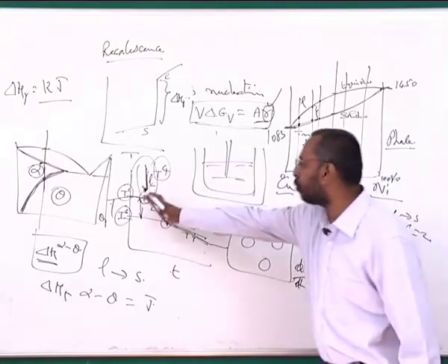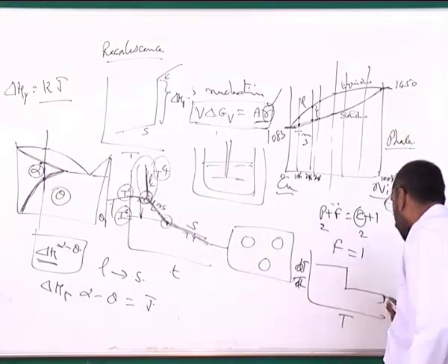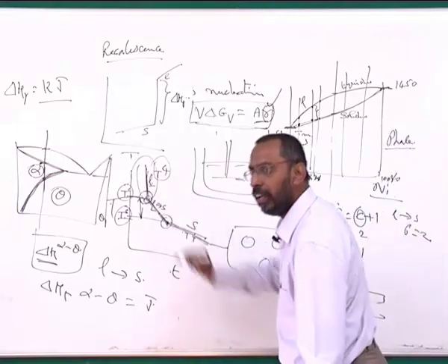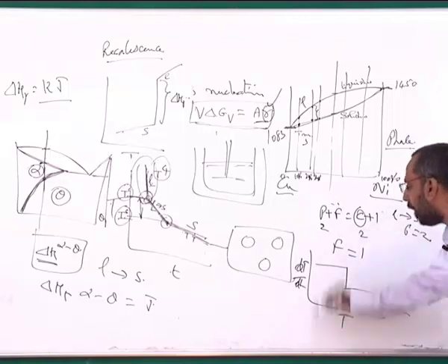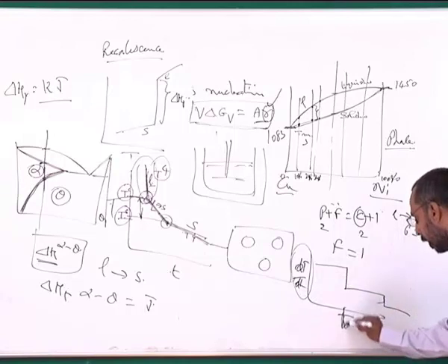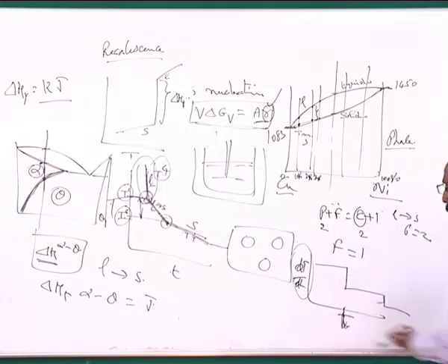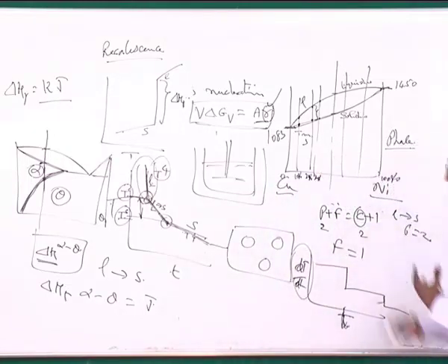Instead of simply a slope change, you see a step now. And again here, for some period it will be constant, and again you will see a sudden step. So you will be able to see a sudden step when you are plotting dT by dt, capital T being temperature, small t being time, as a function of time. If you do this, these kinds of transformations can be felt much more easily.